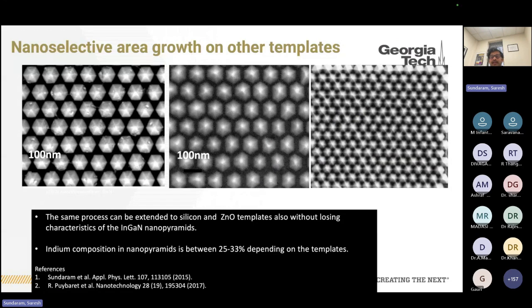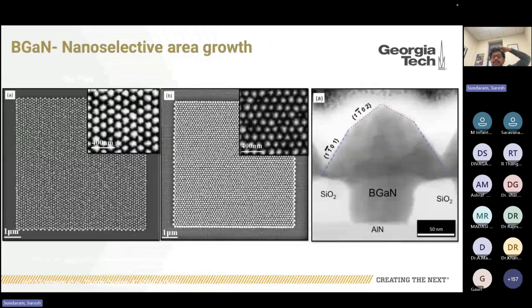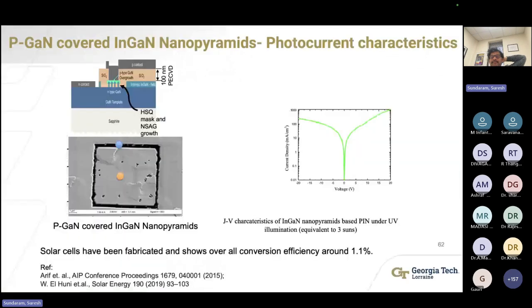We can do it on different templates without any process difficulty. We can use the same process on different templates, and we can use it for different materials also. Here we have used boron gallium nitride on top of these materials, and we have realized single crystalline material. Single crystalline boron gallium nitride with 100 nanometer thickness is really hard to realize, but by using nanoSAG, we were able to realize it without any issues.